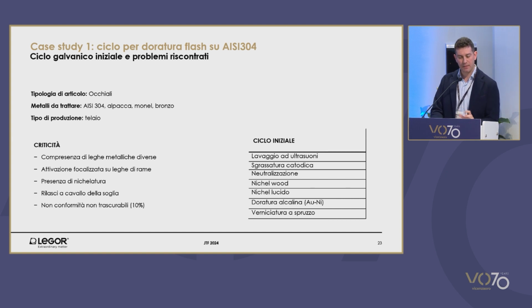Before the project was carried out in LEGOR, the client was too much focused on copper. At the beginning of the cycle, nickel was used. Nickel strike, which is a chloride nickel, and then nickel deposition was often resorted to make the object resistant to corrosion. But the barrier effect, preventing the release of nickel after electrodeposition, was only relying on the spray cycle. 10% of the production